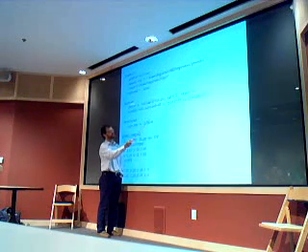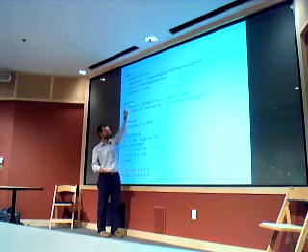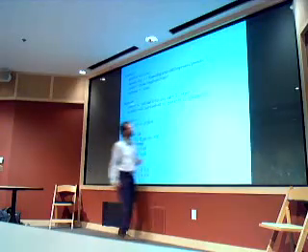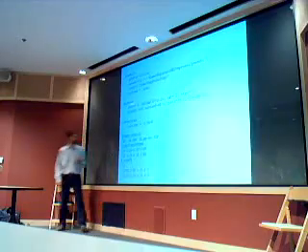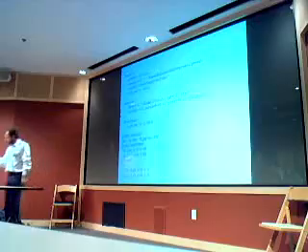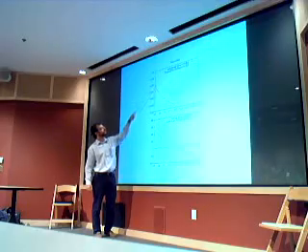to basis functions whose kinetic energy is larger than this EC of 16. And then you have a smoothing parameter. I mean, this step function actually means something which has a finite width, of the order of 2 Rydbergs. All the rest is the same. So what happens? What happens is that the curve now is this green one. Okay?